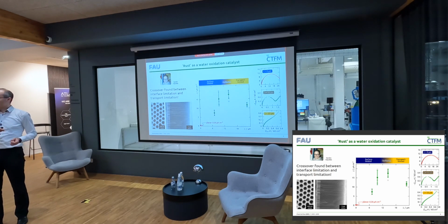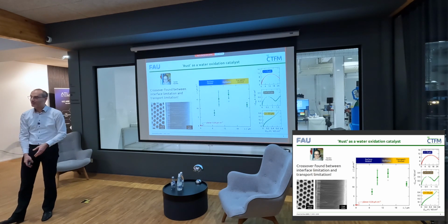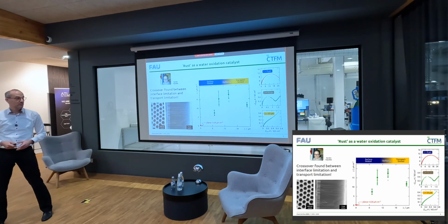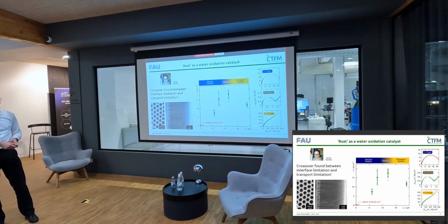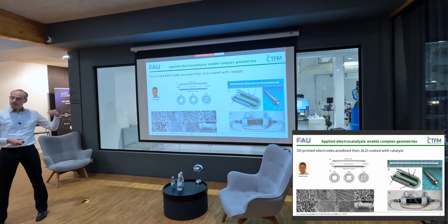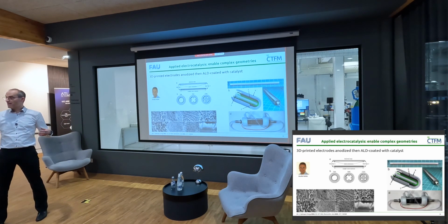And where it becomes interesting, perhaps more on a fundamental level rather than applications, is that you will at some point, when you make the pores long enough, reach the moment where transport becomes limiting, right? That's the moment the aisles in the supermarket are so long that you just waste your time walking around. And we've been able to demonstrate that this is really going from surface limitation to transport limitation by electrochemical impedance spectroscopy. The other direction you can take is more towards application.